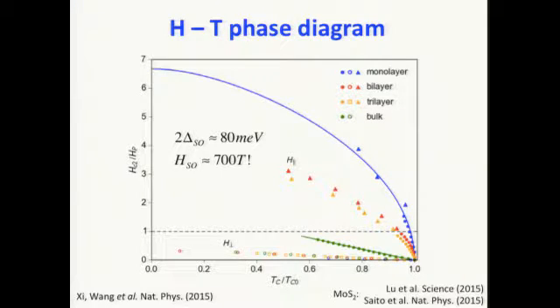Okay. And a more detailed or fair comparison is to plot all the data in this phase diagram, which is the HC2 normalized by the Pauli paramagnetic limit. This dashed line here is the upper limit that is allowed for a BCS superconductor, and the horizontal axis is TC normalized to the zero-field TC. You can see that for the bulk material, the solid dots are the parallel field. For the bulk material, it goes in a linear shape here, which is because of the vortex formation in the bulk material. And when you go to atomically thin materials, it goes into a square root dependence in the small field region, at the high temperature region. And then it goes way beyond the Pauli paramagnetic limit.